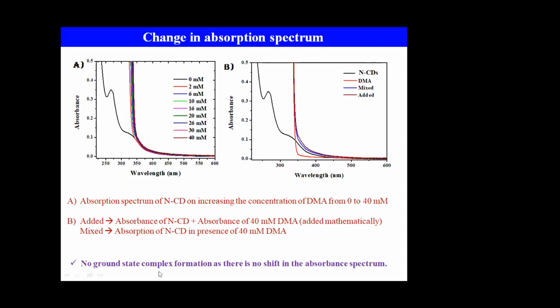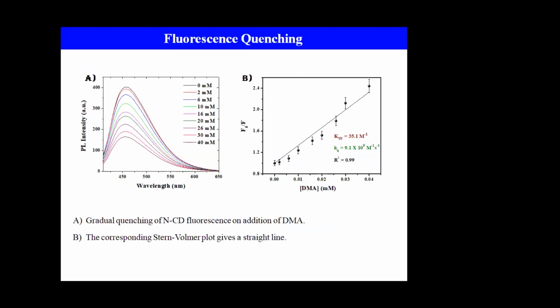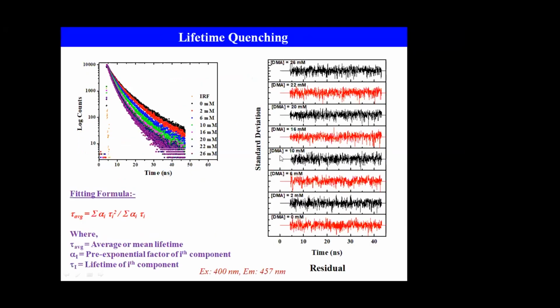As usual, we checked whether a ground state complex is present or not. There is no such ground state complex even with the amine, and we have used it, and that gives information about ruling out the possibility of ground state complex formation. So you have the excited state reaction, it's a luminescence quenching, with a KQ value almost closer to the diffusion control limit of 10 to the power of 9, we have it.